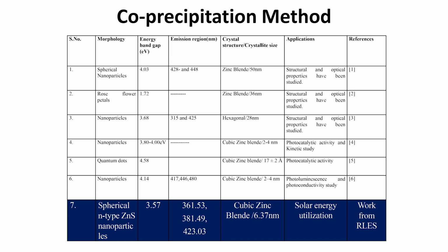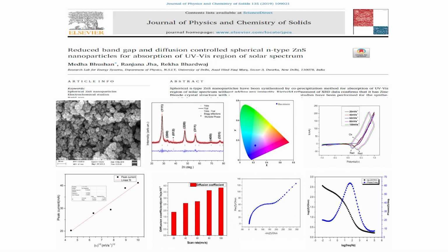And in our case, where we have synthesized the spherical n-type ZnS nanoparticles, we are using them for solar energy utilization. This is the paper which we have published in the Journal of Physics and Chemistry of Solids, on reduced band gap and diffusion controlled spherical n-type ZnS nanoparticles for absorption of the UV-vis region of the solar spectrum. Here in this particular slide, you are able to see the nanostructure which we have developed and the different parameters which we have studied in the ZnS nanoparticles.